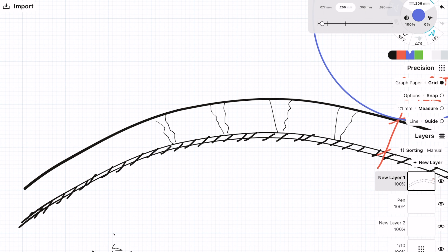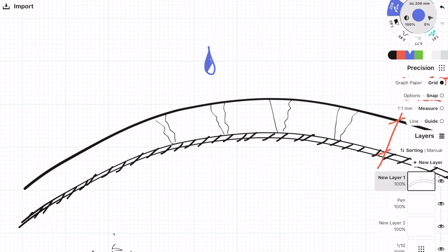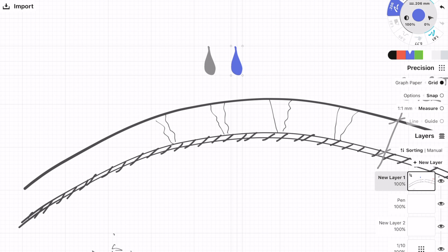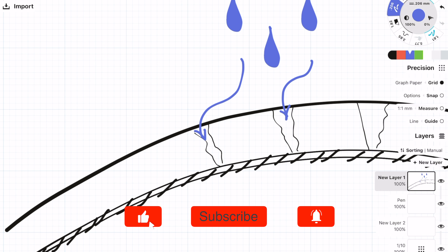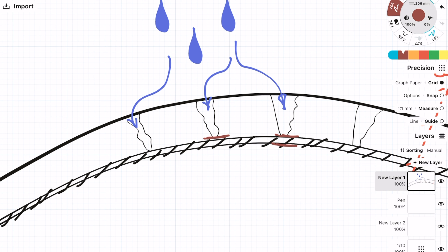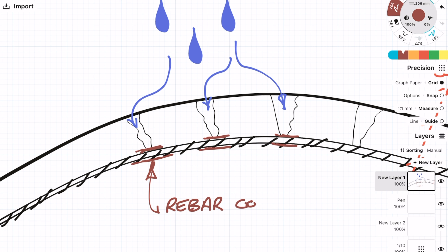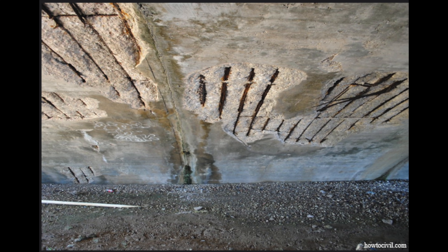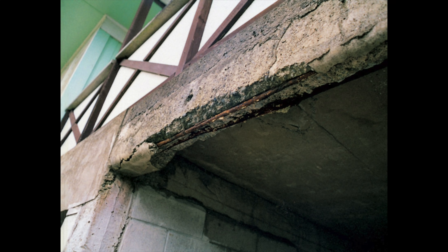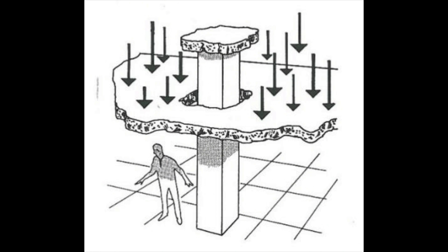Knowing all this, you can probably guess where I'm heading. What I think has happened is the slab has cracked too much around the columns, which is where the tension is. The waterproofing has failed and allowed too much water to be in contact with the top of the concrete slab. In normal cases this should have been okay, but because the cracks were too large, the water has penetrated deep into the concrete and corroded the reinforcement. Over time, this corrodes the reinforcement — the reinforcement rusts and expands, which causes the concrete to spall or break away. This spalling or concrete separation is what Building Integrity called delamination of the concrete, which causes the slab to fail in punching shear.